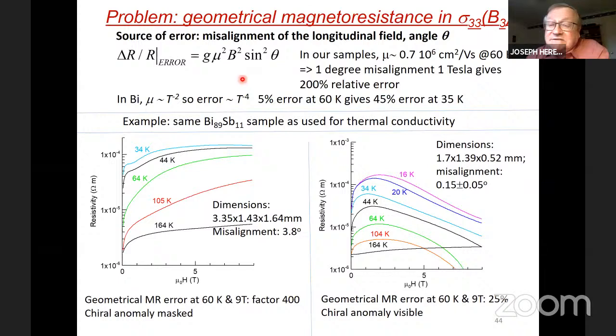Furthermore, the mobility in bismuth scales with T to the minus 2. It goes in squared here. So the temperature dependence of this error is T to the minus 4, which means that you have almost an order of magnitude more error at 35 Kelvin than you have at 60 Kelvin.